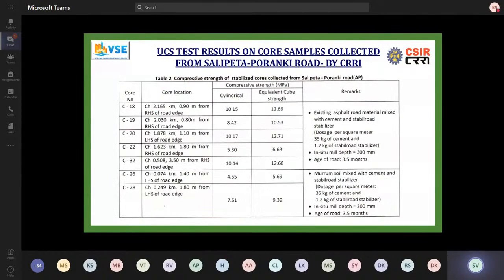Again, very good strength. Actually, in rural roads, we follow IRC 72, which requires a minimum strength of 3 MPa. But in our case, we have achieved much higher. So over a period of time, we have to reduce the dosage of cement and additive to get the optimal. It doesn't make sense to use so much material as well. So we're working on it.